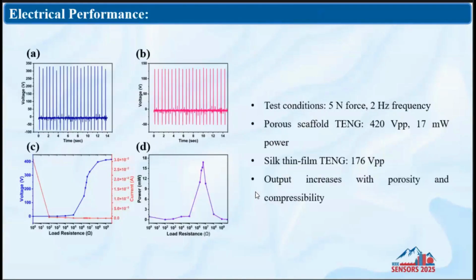After that, we looked at the electrical performance, how much power it is able to generate. The first one is the silk porous scaffold. It generated almost 420 volts peak to peak. And as you can see in B, the silk thin film generated almost around 170 volts peak to peak.